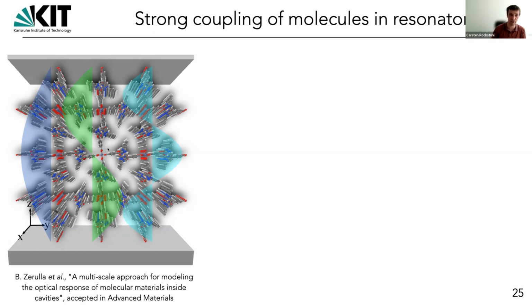You put this molecule in there, and you would like to study whether the excitations in that molecule can strongly couple to these resonator modes. The procedure here is then straightforward. This is a molecule called a zinc-based phthalocyanine, which can be experimentally arranged even in a periodic manner, thanks to a technique called surface anchored metal organic frameworks, SURMOF in short.